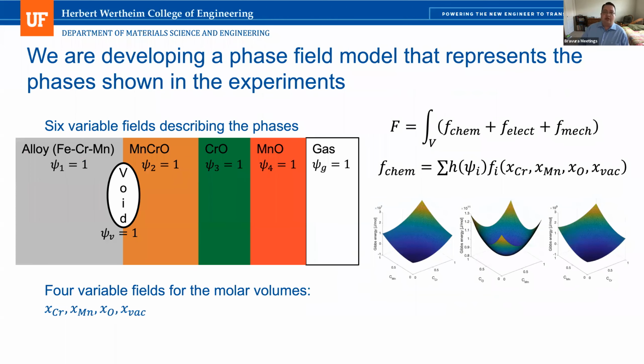Now we are developing our phase field model, which is going to allow us to look at the actual growth of the oxides and to spatially resolve the evolution of the oxides over time. And the way that we do that is we represent various aspects of the microstructure with variable fields that evolve and change over time. So within our domain, anywhere where this variable psi1 is equal to 1 will be an alloy. And anywhere psi2 is equal to 1 will be the spinel, psi3 is equal to 1 will be the chrome oxide, and so on.